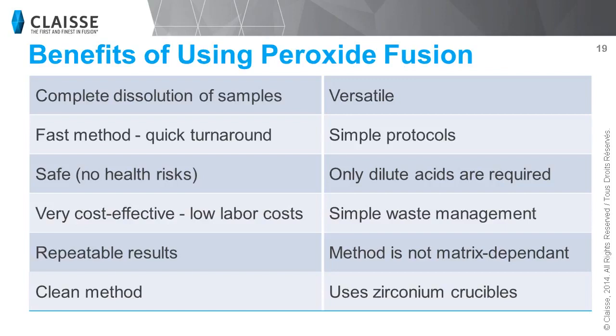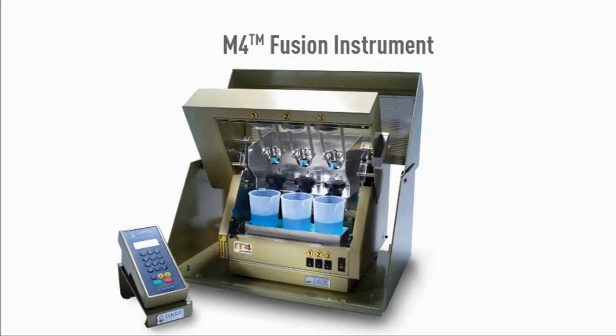This is very simple and doesn't require any strong acids such as perchloric acid or hydrofluoric acid. The waste management is then facilitated and fusion is a clean method to prepare your sample. The heat needed to have the peroxide react with the sample is controlled by the instrument in a very reliable and repeatable way, making it stable and safe. Also, peroxide fusion is performed in zirconium or nickel crucibles, which are rather cheap compared to platinum.